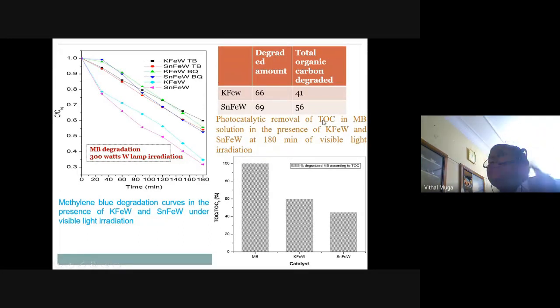Now, in addition to that, total organic carbon also we estimated. Now, methylene blue, after 180 minutes of irradiation, you see that it is having about 100% total carbon. But KFEW, 60% only. And SNFEW, only about 50% carbon is remaining now. Okay.